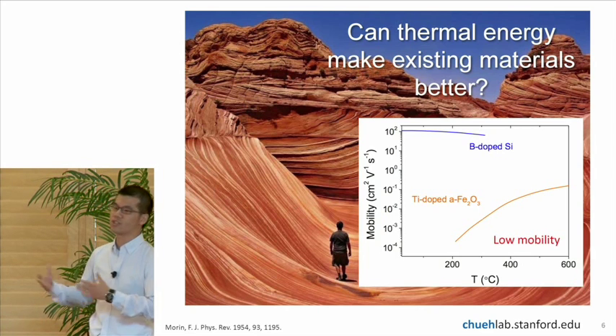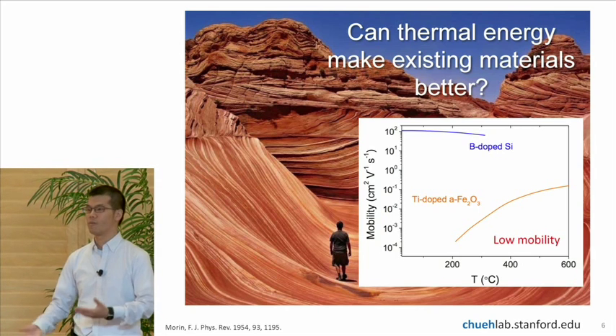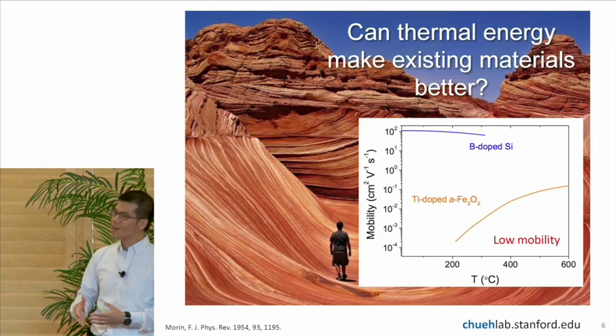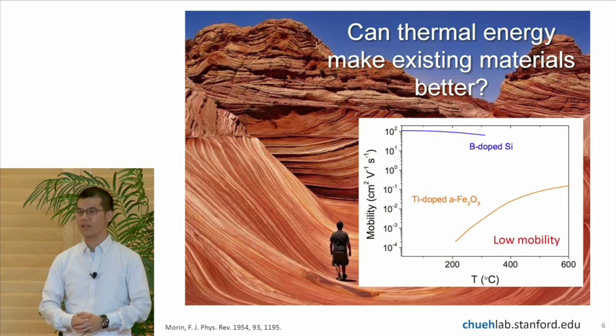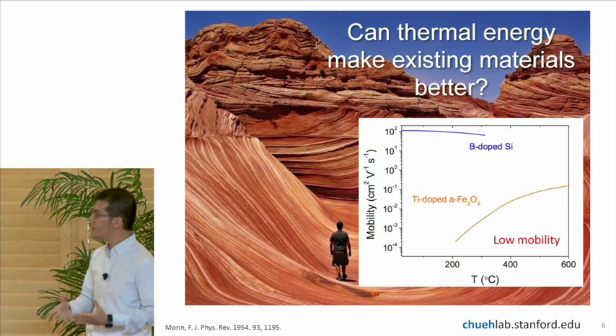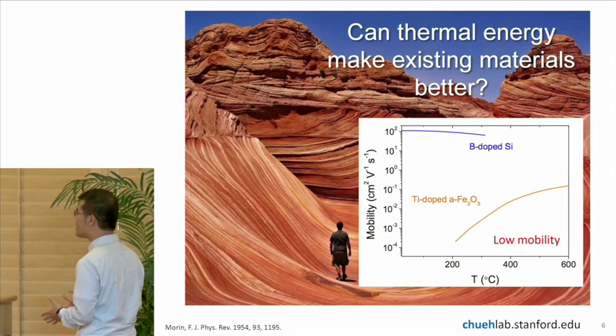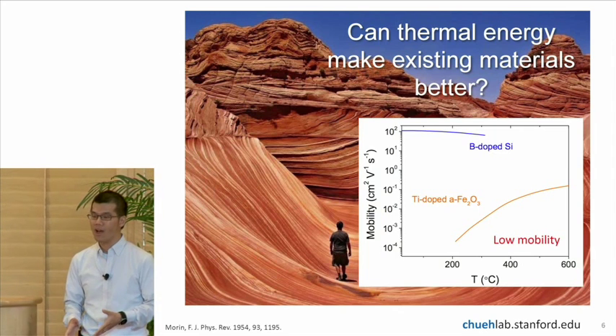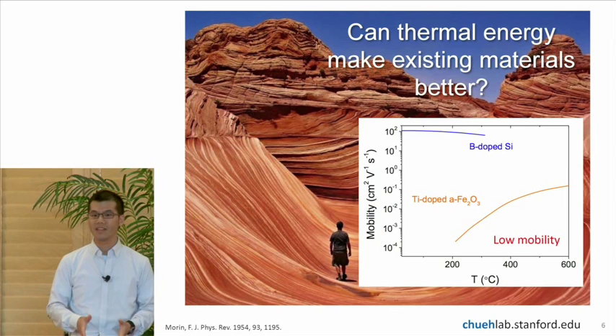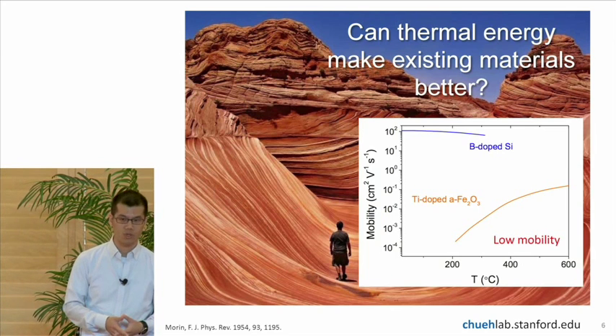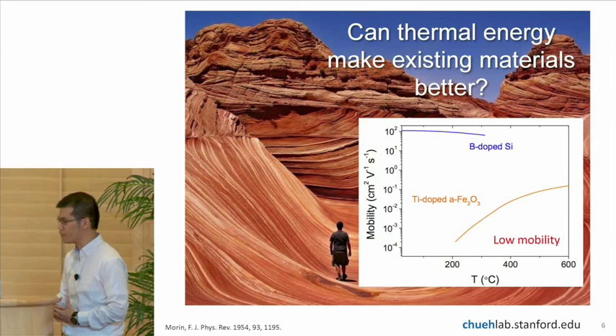You can think about doping, but that just increases the concentration of the majority carrier. There is not a lot of routes. If you nanostructure, that's fine too, but again, you're not changing the mobility. So the fundamental limitation of these highly stable, abundant material, like iron oxide, is simply that the mobility isn't good enough at room temperature. So let's up the temperature and see what happens.